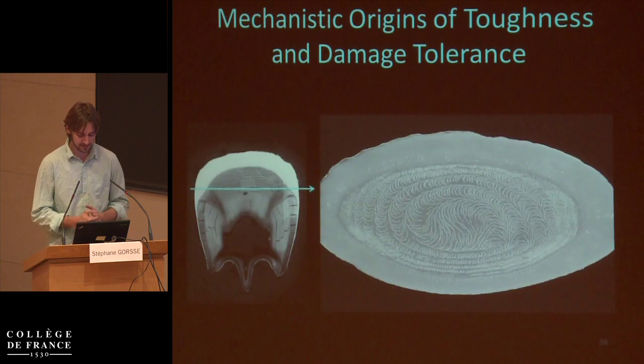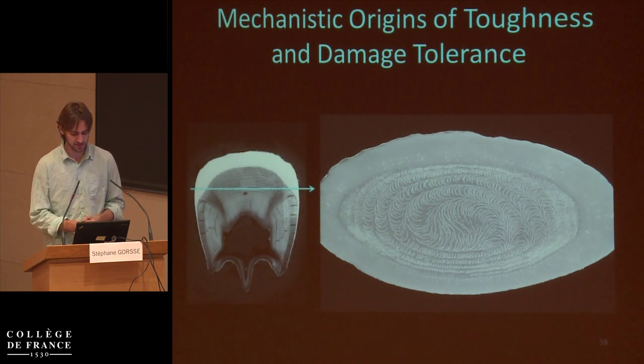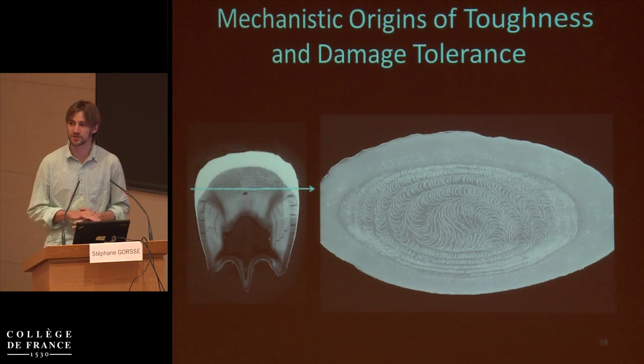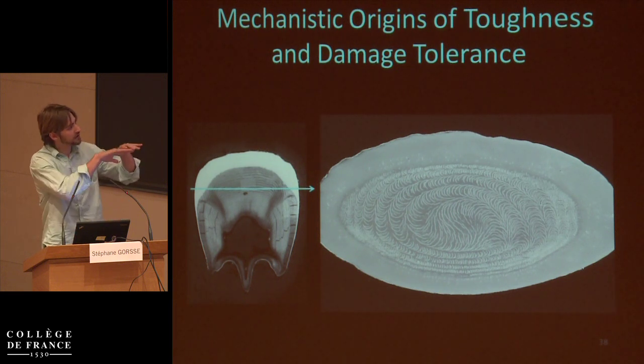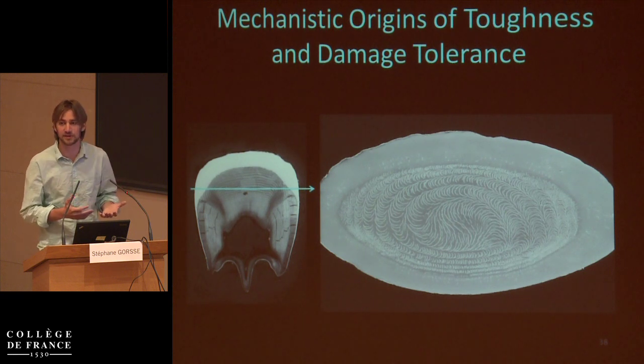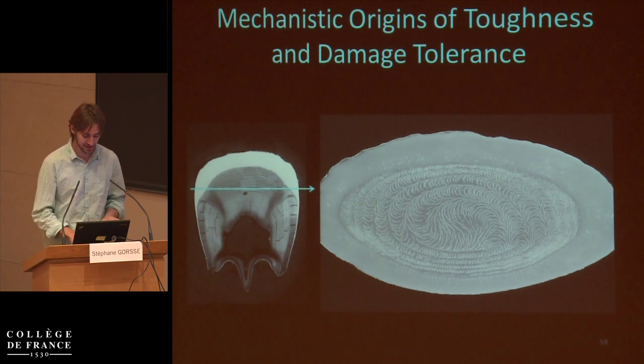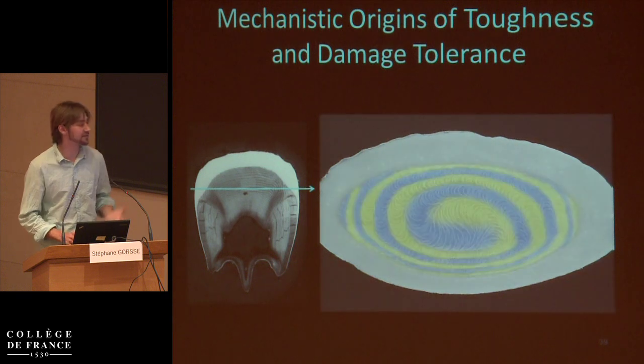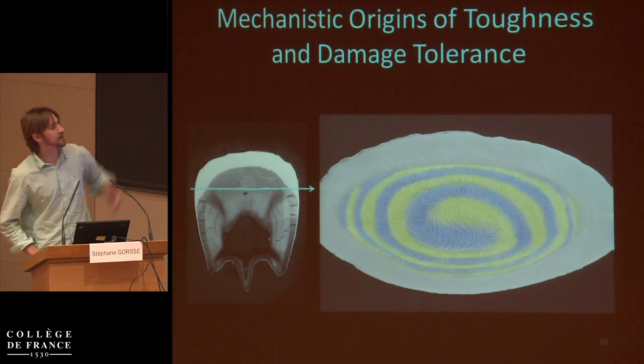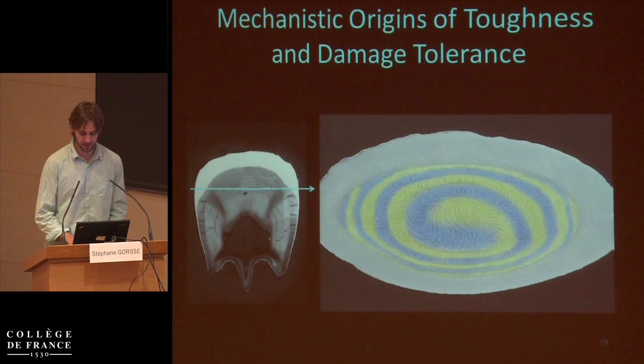And then if we look at a coronal cross-section, we see something very puzzling, which is also a lot of these microfractures. But if we're looking at a layered architecture, you'd assume that a layered architecture over a curved surface is kind of like an onion. And when you make a cross-section through an onion, you'd expect to get concentric rings. But if I false color this, the pattern that pops out is a double spiral, and that's quite puzzling.